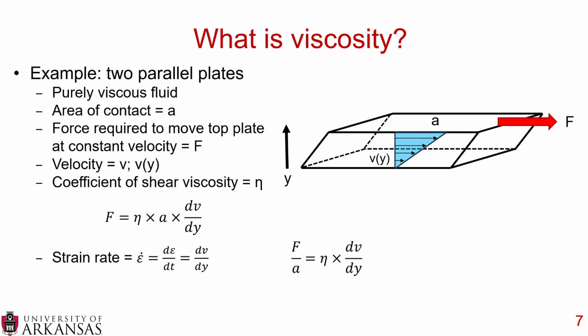So you can replace that into our equation and divide by a. So F divided by a equals eta times dv over dy. And then substituting in that epsilon dot, you get the stress equals the coefficient of shear viscosity times epsilon dot. And so this is how we get the equations behind viscosity.